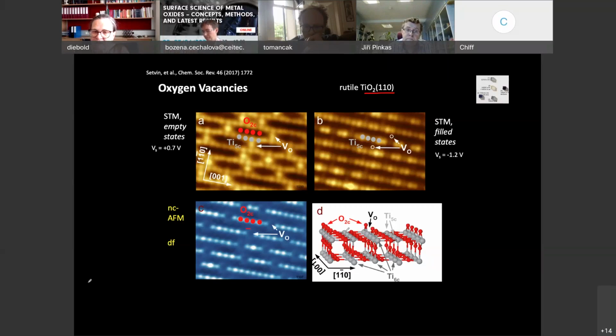So this is what you get out of one of these theoretical calculations. This would be a very stable surface. This is the most common imperfection, defect, an oxygen vacancy, a vacancy at the position of the oxygen. And if you look at non-contact AFM, if you look at the frequency shift, that's exactly what you see. You can see oxygen atoms aligned in nice rows. And some of them are missing. Those are the oxygen vacancies. So we can actually directly see these defects.